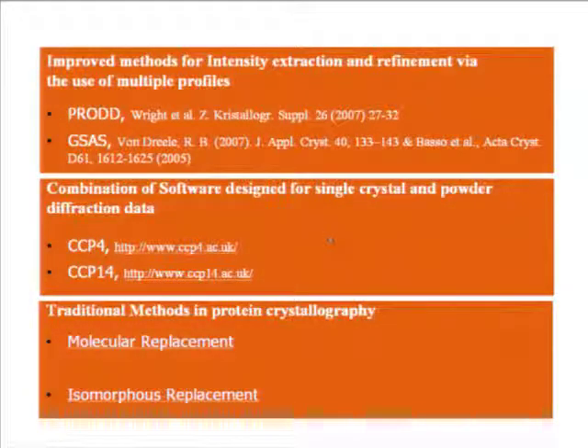So we use both single crystal and powder software in order to solve the structures. John mentioned the program PRODD, developed by him, which we use for intensity extraction via the Pawley method. And of course, we use GSAS to refine the structures using stereochemical restraints and multiple patterns. That's very important. We don't refine a structure using only one powder profile because it's more difficult and the information content in many cases is not enough.